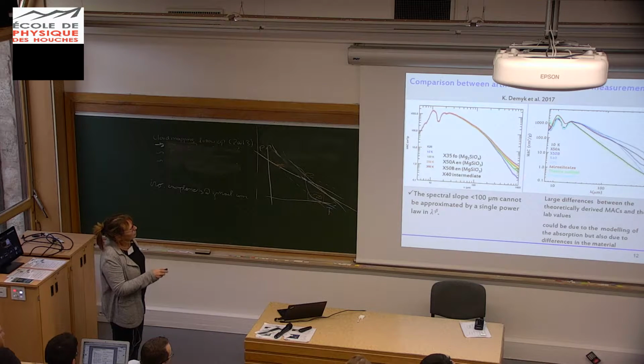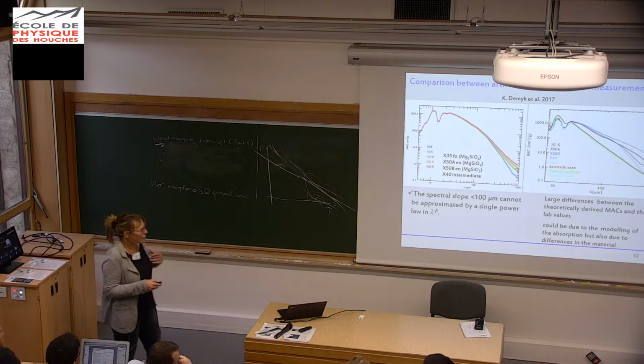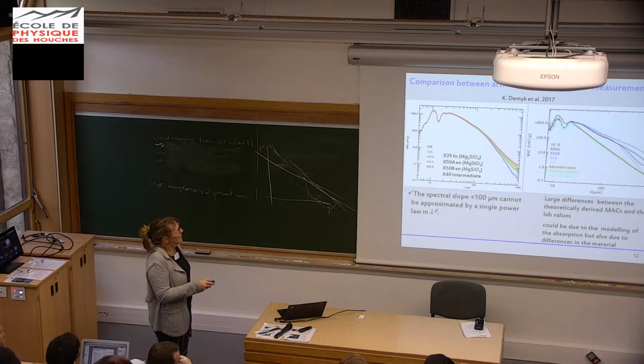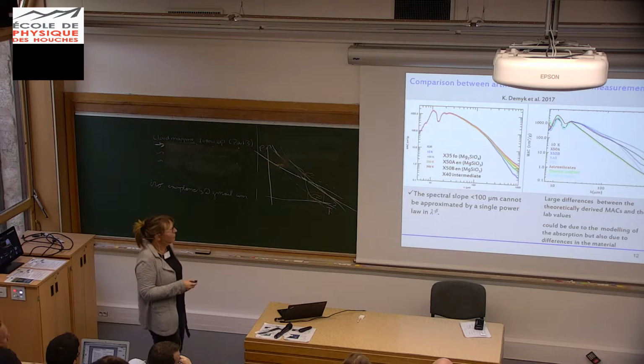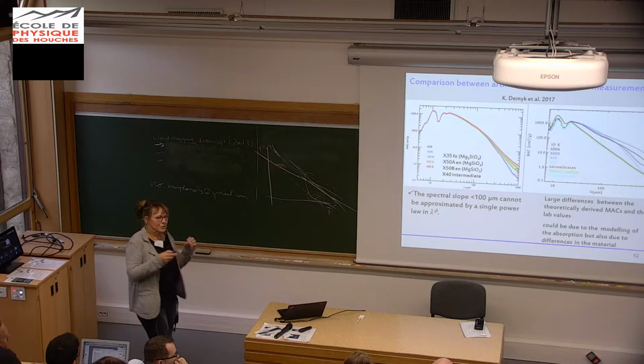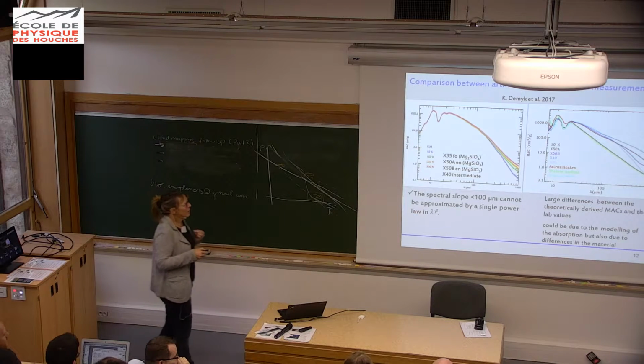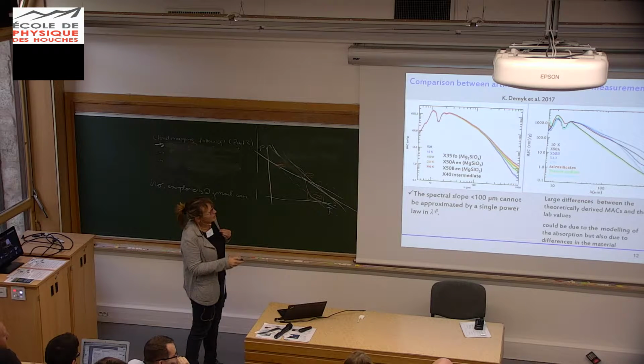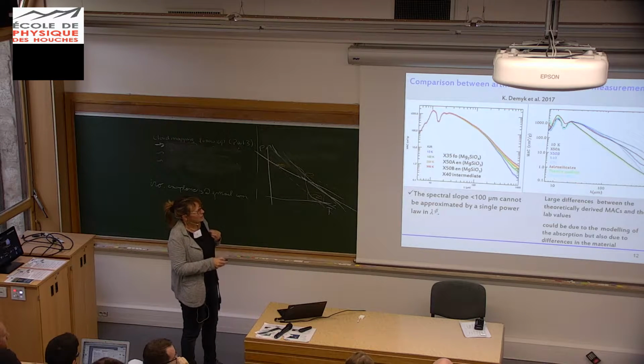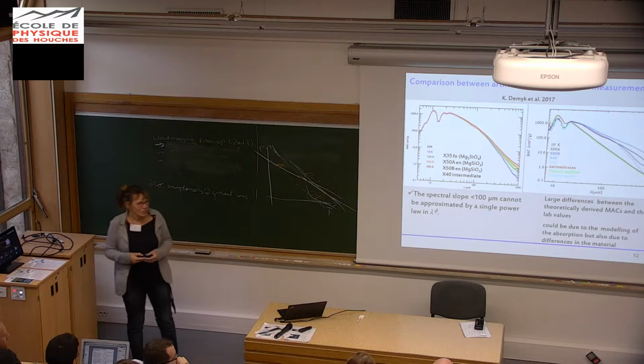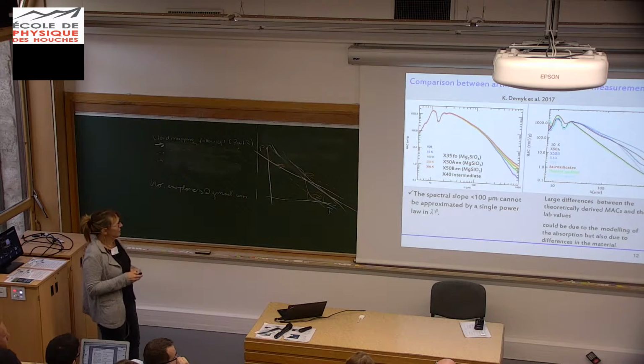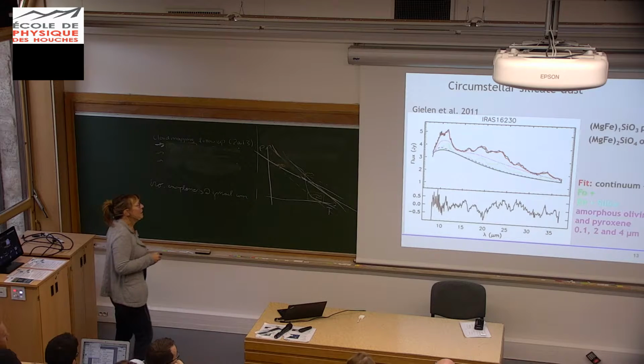Very interestingly - that's why I wanted to show you - if you compare these measurements to the astrosilicates derived by Draine, for example, or the silicates based on the THEMIS model, you see there are really big differences between the laboratory studies and the theoretical approaches to the spectral data of the material. So keep this in mind - there could be large differences.